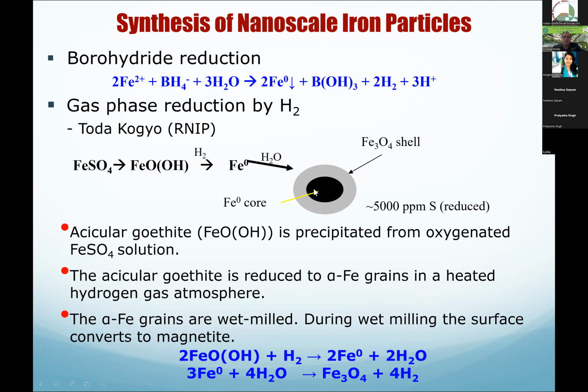So the nanoparticles would look like this. You will have an iron core inside, and then you will have this Fe3O4 shell outside. And during this process, you could have some sulfur introduced into that. Sometimes in our studies, we saw that sulfur makes some difference.